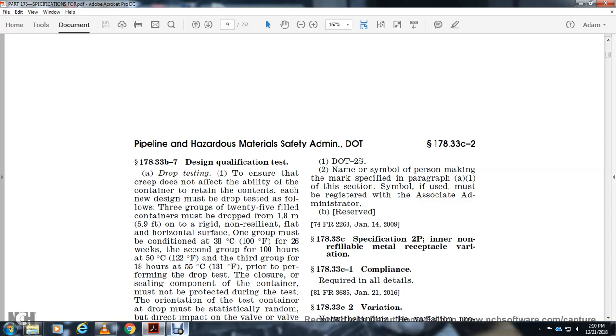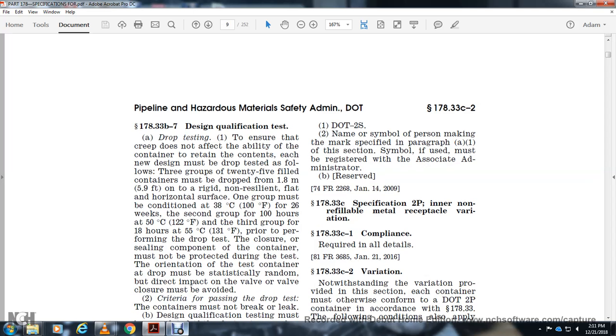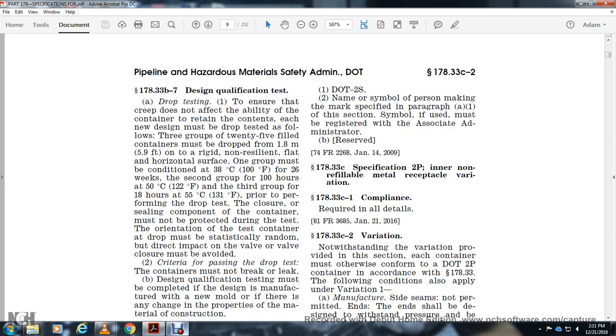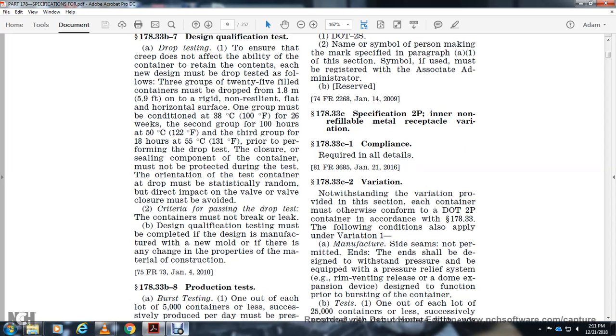178.33b-7 Design qualification drop test. Ensure the creep does not affect the ability of the container to retain its contents. The design of each new design must be drop tested. The test is for all three groups of 25 filled containers, which must be dropped 5.9 feet onto the top of a rigid, non-resilient, flat, horizontal surface. One group must be conditioned at 100 degrees Fahrenheit, the second group at 122 degrees Fahrenheit, and the third group at 131 degrees Fahrenheit prior to the drop test. The closure with the sealing component must not be protected during the testing. Orientation of the test: container drop is statistically random, avoiding direct impact of the valve and valve closure. Criteria for passing the drop test: the containers must not break or leak. Qualification testing must be completed with the design manufacturer for a new mold, or if there is a change in the properties of the material of construction.